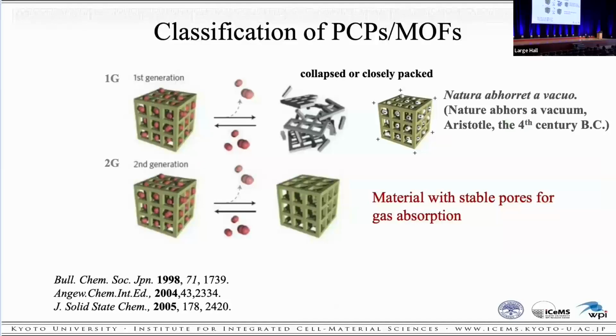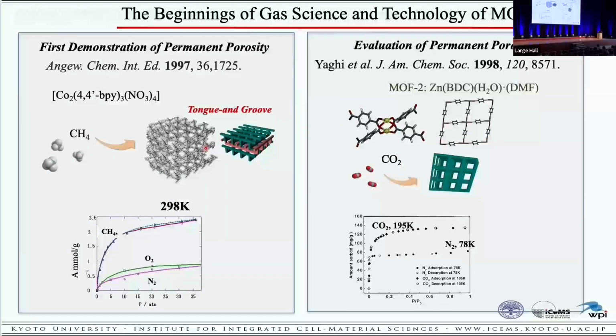Second generation MOF are truly robust porous structures. In realizing a second generation MOF with permanent pores, it is necessary that the MOF is stable with nothing in the pores, and that gas is reversibly taken up. We have synthesized a porous material in this scheme. In fact, it can reversibly adsorb methane, oxygen, and nitrogen. On the other hand, carbon dioxide has been adsorbed by materials synthesized in this scheme.